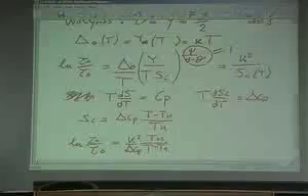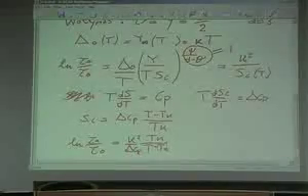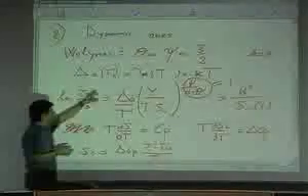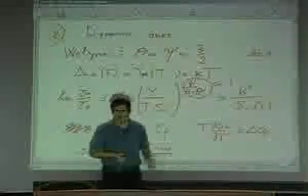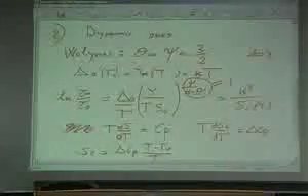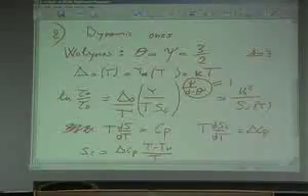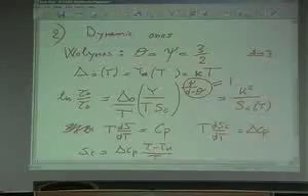But again, at least to me, all the assumptions you make to arrive here are very suspicious. Not that I think there is something hidden; I just really don't know if they are right or wrong. Maybe I can already comment on one of the assumptions, which is that delta 0 is equal to upsilon, which is equal to kT, and this is strange. This means that when I decrease the temperature, the effective surface tension decreases, which is exactly the opposite of what one would naturally have thought.